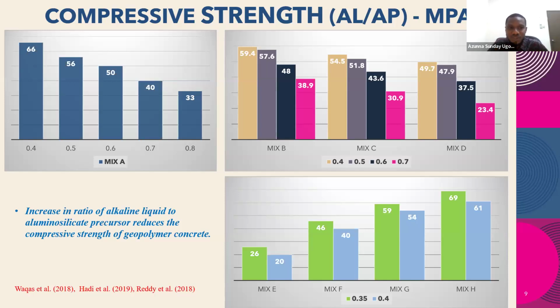And on the other hand, if you use a lower alkaline liquid to binder ratio, you're most likely to get a higher strength, because the binder content is going to be high. Then the alkaline liquid may not be as high as it would if the ratio is much higher, but you're going to get a very good strength, which is also the same for normal concrete. If you use say 0.35 or 0.4, you're in a better position to get a good strength. So most times, like I said, the ratio that is acceptable or recommended for the design of geopolymer is between 0.35 and 0.6. So if you're using 0.7, most times your strength may be very, very small.